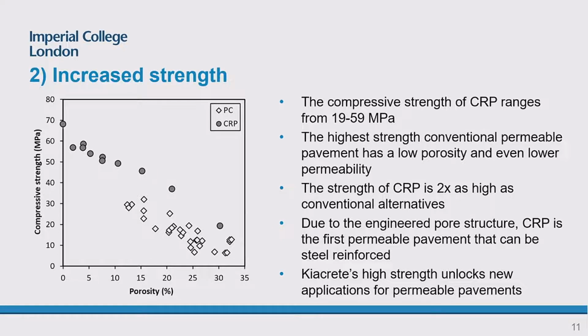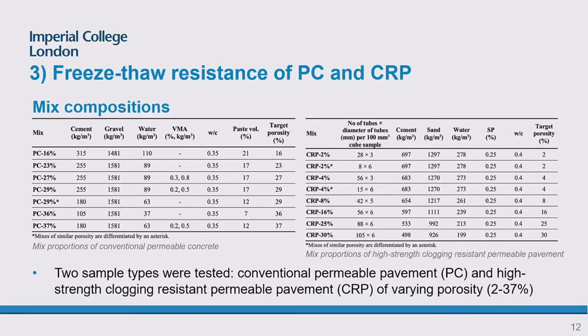The second benefit is the increased strength. So the strength of CRP or Keyacrete is twice as high as the conventional systems. And in addition to that, that strength can even be increased by reinforcing it, either with fiber reinforcement or steel bars. This is something that the conventional permeable pavements cannot benefit from because of the contact of water and reinforcement causing corrosion and damage to the pavement. But because we changed the pore structure of permeable pavements, we can actually achieve that. And not to mention that we can change the pore structure, change the concrete that we are using just to play with the different parameters that are needed.